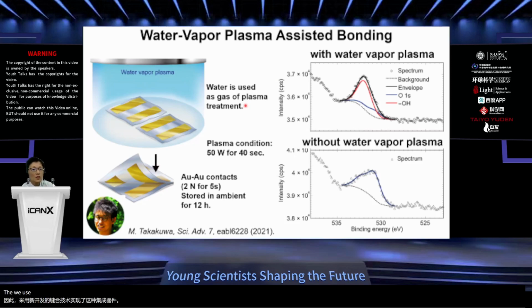We use a water vapor plasma treatment onto the gold surfaces. And after the treatment of the gold surfaces, we gently laminated these two gold electrodes, and we stored the laminated gold interface in ambient air for several hours. In this experiment, we left this film for 12 hours. But anyway, we didn't apply any thermal process or any additional pressure. So we just stored this sample in ambient air for several hours.